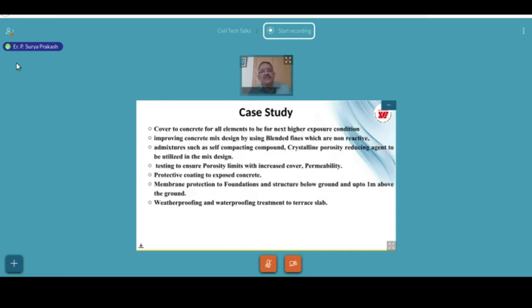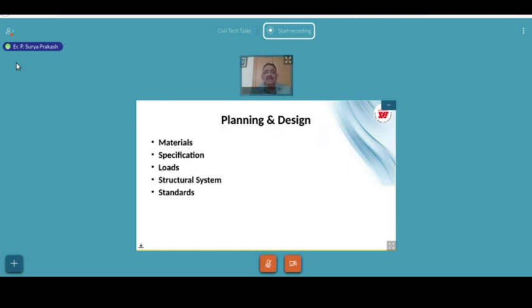And the cover to concrete for all elements to be for next higher exposure condition. Improving concrete mix design by using blended fines, which are non-reactive, fines to be non-reactive, blending. Admixtures such as self-compacting compound, crystalline porosity reducing agent, and testing to ensure porosity limits within increased cover, permeability, and protective coating to exposed concrete, membrane protection, and weatherproofing and waterproofing to be maintained for all the exposed. So materials, specifications, loads, structural system, and standards. These are the parameters we have to cover while doing the planning and design for the longer life.